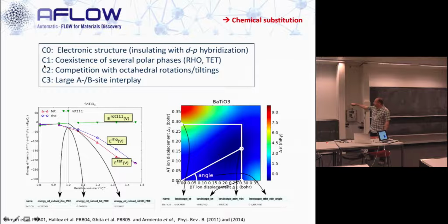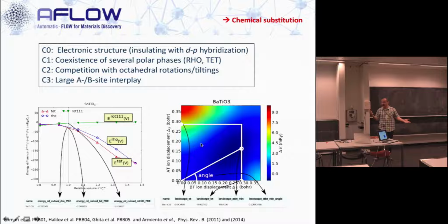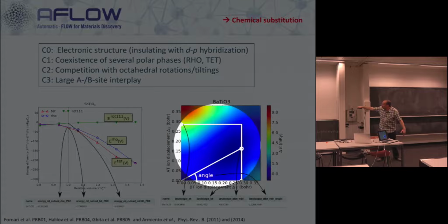Okay? For criterion 3, what we did is to play a game, right? We took the ABO3 structure and we displaced the A and the B site independently. So this is the total energy response to the A and the B site independent displacement. Okay, the idea is that when we have a distortion to which both A and B site contribute, we have a minimum somewhere in the middle of this diagram. When the system is mostly A site or B site, the minimum will sit here or here.